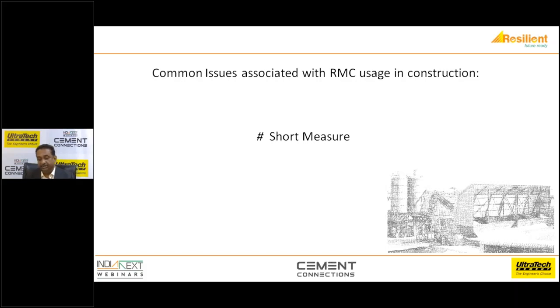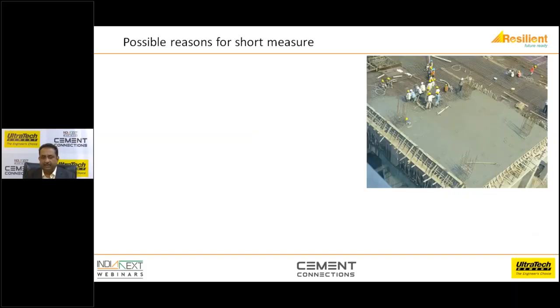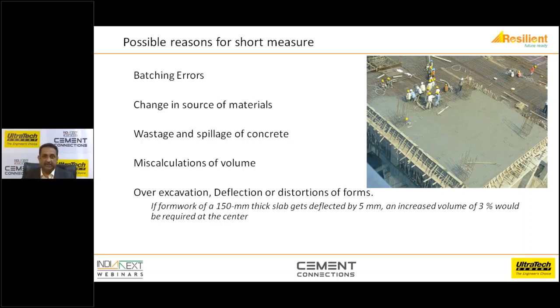Then you have the problem of short measure, which is again one of the very common problems, where you see that we had ordered 45 cubic meters of concrete, but I had to consume 47 cubic meters of concrete. 2 cubic meters of concrete was in excess. Now, why does this happen? This can happen due to many reasons. It can happen at the batching plant because of batching errors. Your computer might be showing that this much concrete has been batched, with materials in the same proportion as you have designed, but that could be a slippage. There could be a build-up of material inside the weigh hopper, which is always giving you erroneous readings. These are the issues which can happen.